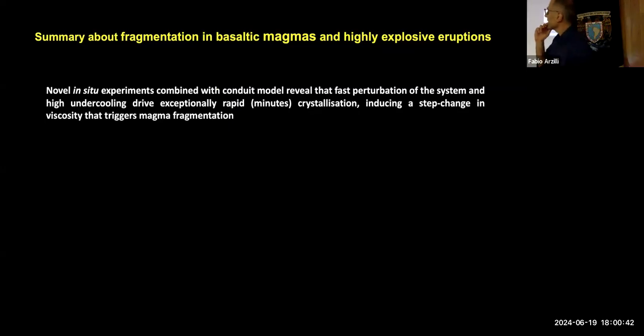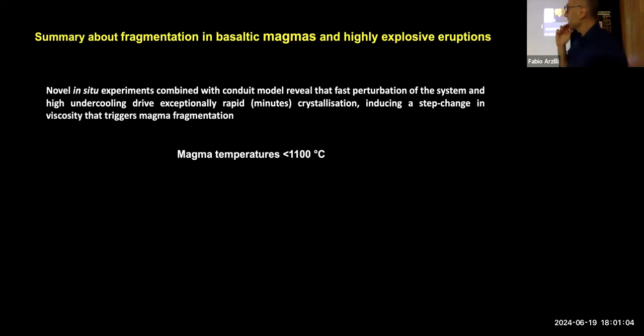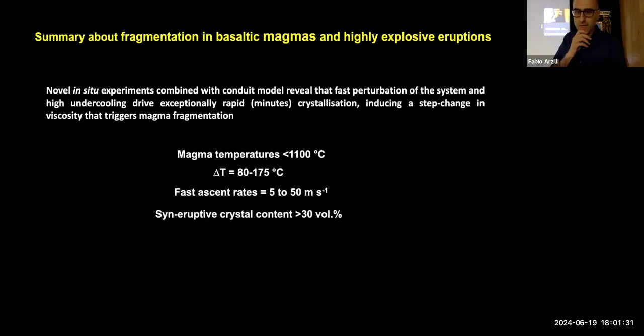and so the conduit dynamics works exactly as I said before, with the same dynamics. And just to summarize about fragmentation in basaltic magmas, we performed these in situ experiments where we perturbed the system quickly, so we perturbed the undercooling quite quickly, and we obtained basically magma fragmentation where the initial temperature of the magma was lower than 1100 degrees Celsius, undercooling between 80 and 175 degrees Celsius, fast ascent rate at the bottom, close to the magma chamber, 5 meters per second, up to 50 meters per second in the top part, and syn-eruptive crystal content higher than 30 volume percent was produced by fast crystallization during ascent, and magma viscosity around 10 to the 6 Pascal second where fragmentation can occur.